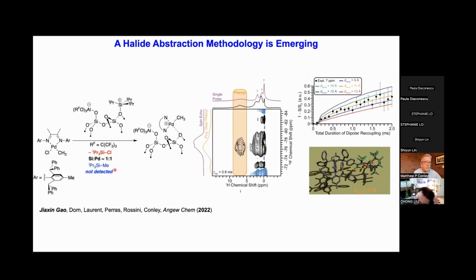And these react very nicely in halide abstraction reactions. For historical reasons, we went to this diimine, this bulky diimine palladium methyl chloride. There's a lot of information we could extract from this one experiment. You could expect that the silylium could go for the chloride or the methyl. So we only see TIPS chloride in solution and no triisopropyl methyl, which makes sense because silylium ions have some of the highest halide ion affinities that are known.